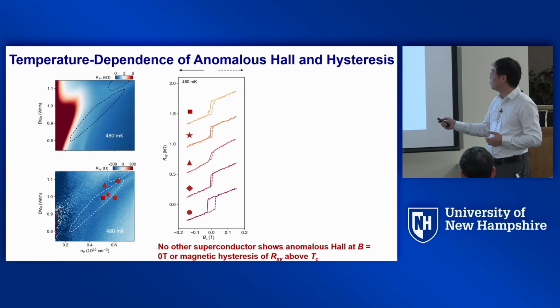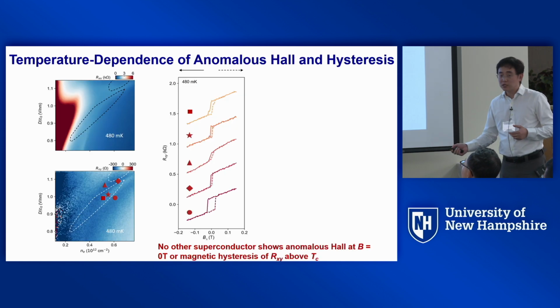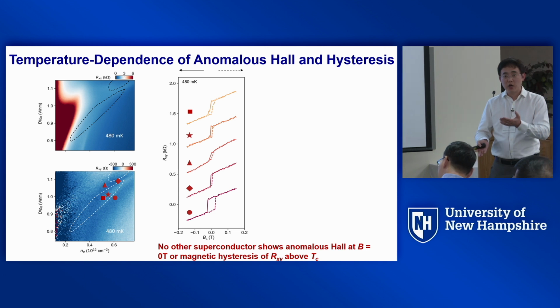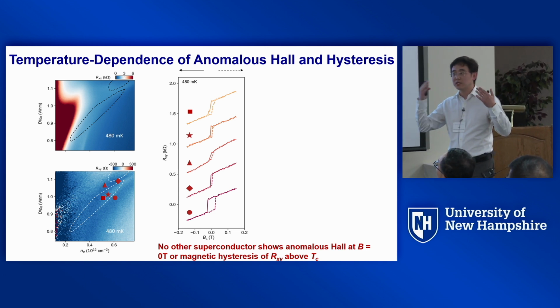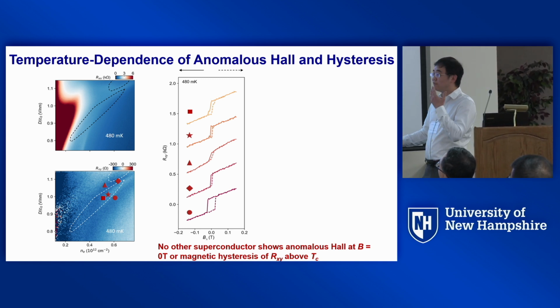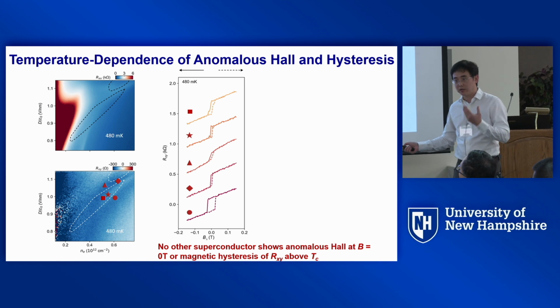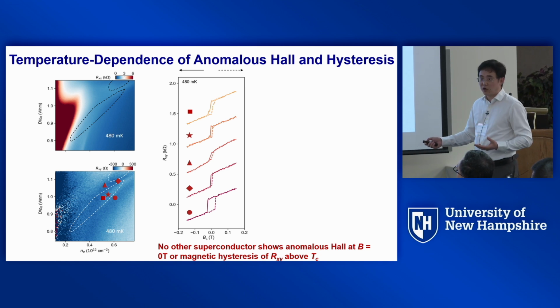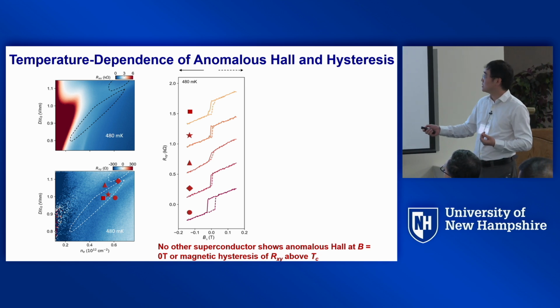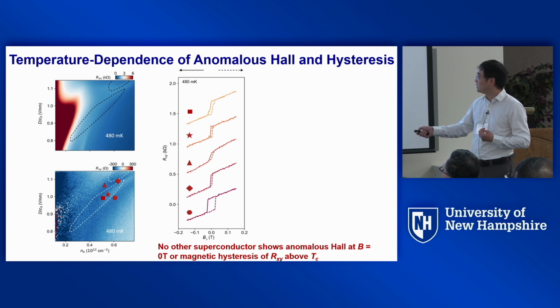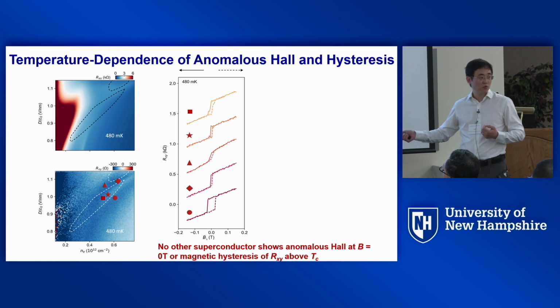Now let me show you more data. Okay? One thing you can ask is, how about above Tc? Okay, when the superconductivity is gone, do you have any signature of time reversal symmetry breaking, valley polarization, or anomalous Hall? And the answer is yes. Okay, this is 480 millikelvin. This dashed line outlines the two ovals, SC1 and SC2. You have clear anomalous Hall both inside and outside the superconductivity region 1.